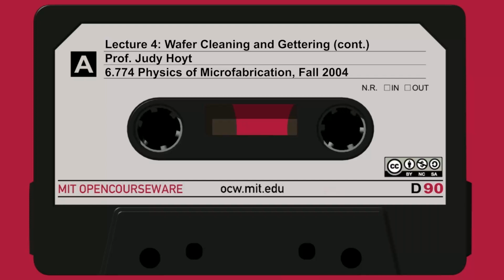So it didn't do the RCA clean. And you can see, look at the amount of calcium here, reasonably high quantities. These are all measured in units of 10 to the 10th atoms per square centimeter. So if you looked in a square centimeter, imagine counting the atoms, you'd find 10 to the 10th of them, roughly. Well, actually, in this position, you'd find 17 times 10 to the 10th, or roughly 1.7 times 10 to the 11th per square centimeter sitting on that surface. So it's a way of quantifying that.